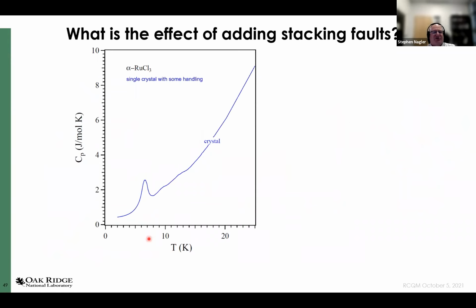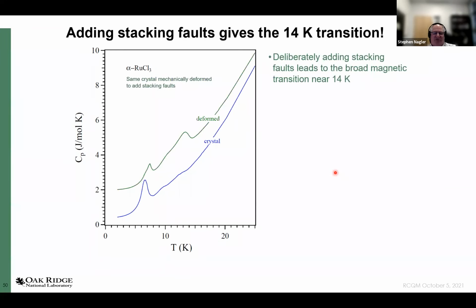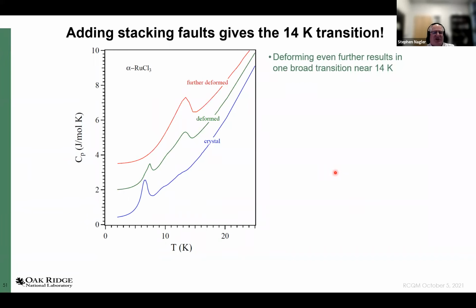If I handle the crystal and remeasure the specific heat, I find this is broader and I start to see some other structure. In fact, our colleague J.Q. Yen deliberately did some mechanical work on some of these crystals. What he found is that as you work it, you lower the specific heat at 7 Kelvin, and you start to see some response at other temperatures, most notably 14 Kelvin.